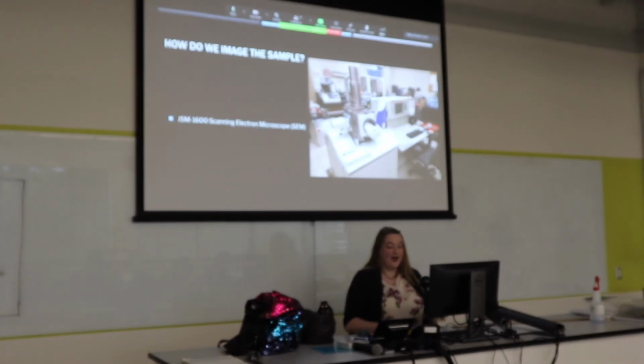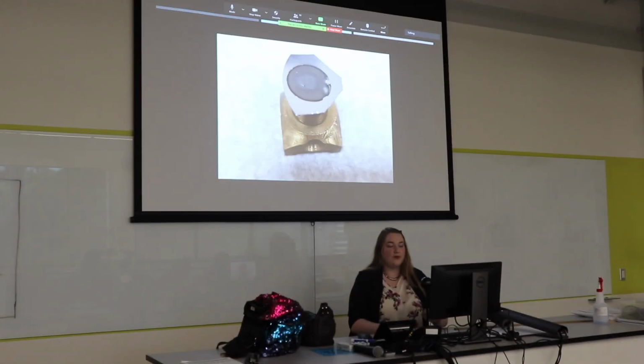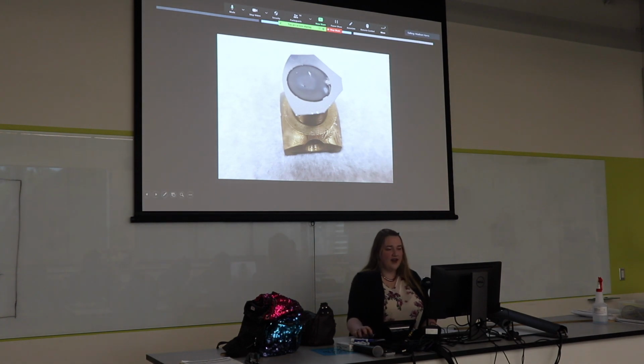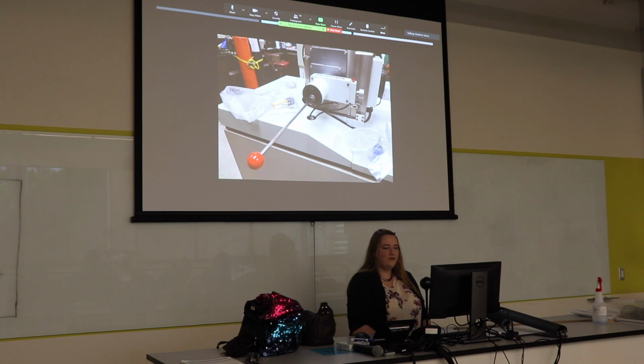So I'm going to just walk you through how to use this. First, we prep our sample. We have a film that has grown on top of some substrate. There's a little circle here. That's because there was a little air bubble when the film was growing. And we use carbon tape and put it on top of this little stage mechanism that has a hole with threads on the inside. So we screw this stage mechanism onto this long pole. The pole has a disc on it to seal into this vacuum chamber, where we press this red button and wait for it to get down to the right pressure, which is almost vacuum-like.